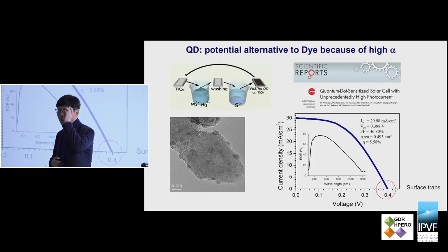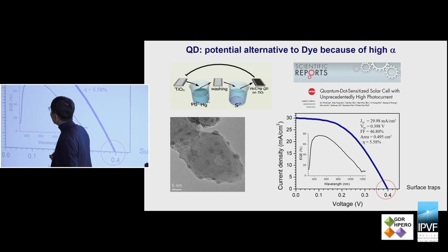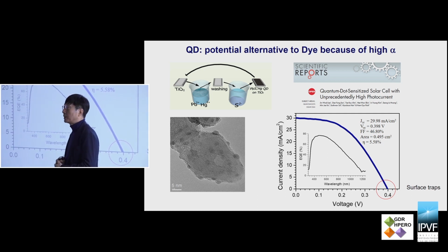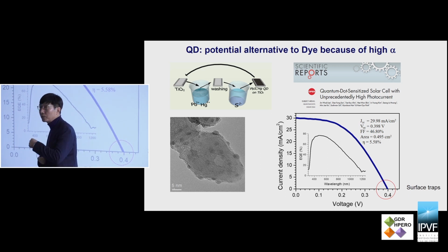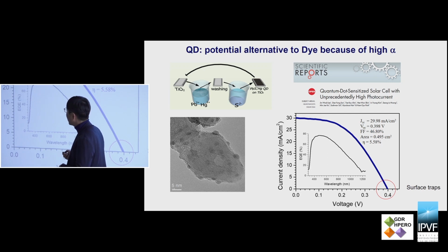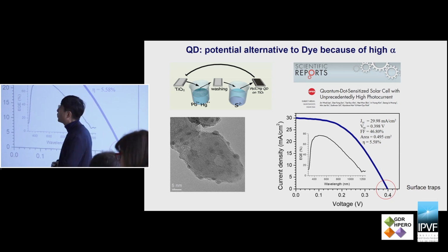One very good candidate example is inorganic quantum dot material. Actually, we also studied inorganic quantum dot materials, for instance, lead sulfide. Bulk lead sulfide is not good for photovoltaic material because the band gap energy is about 0.5 eV. But if you decrease the size, then you can see the quantum size effect. For lead sulfide, if you decrease the size to less than 2 or 3 nanometers, then the band gap increases to 1.1 eV.